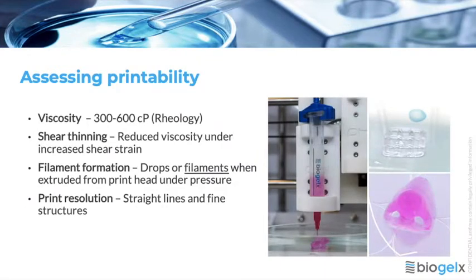During in-house development of these bioinks, the first thing that we look to optimise for is the viscosity, which is something that we can assess by rheology. And we set ourselves this window of 300 to 600 centipoise, with the lower limit being one which gave us reasonable viscosity for the shapes that we printed to bear their own weight and allow them to be printed in layers over each other without spreading too much. And then the upper limit is really to try and reduce the amount of back pressure you would need to apply to extrude the material from the print head. So this limits the stress that the cells contained in the bioink are put under.